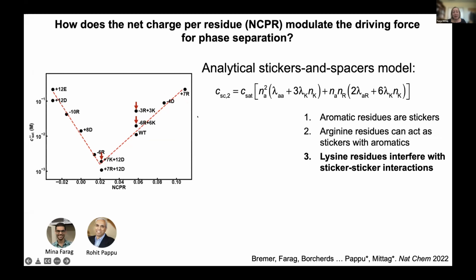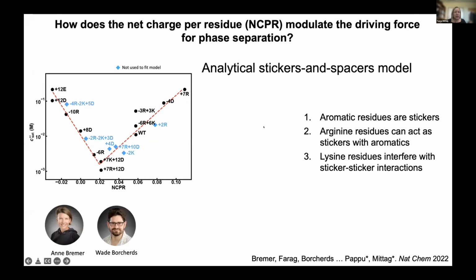And to test whether this made sense or this was just by coincidence, we could fit this, right? We added a lot of other variants that were not used to fit these parameters, and they nicely fell onto this V-shaped plot. And so overall, this makes sense that we came to the conclusion, okay, aromatic residues are stickers. Arginine residues can act as additional stickers together with aromatics, and lysine residues really interfere with sticker-sticker interactions.